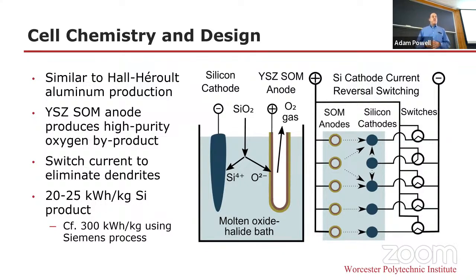And in particular, the work of Uday Pal over the last 12 years or so has led to a new molten salt bath chemistry that was an order of magnitude better than everything else in 5 key metrics: solubility, the conductivity, viscosity, volatility. And so this allows you to dissolve silicon dioxide and use a zirconia, yttria stabilized zirconia solid oxide membrane anode. So this electrochemically pulls the oxygen from our molten salt electrolyte through a solid zirconia electrolyte into an inert anode where it becomes oxygen gas.